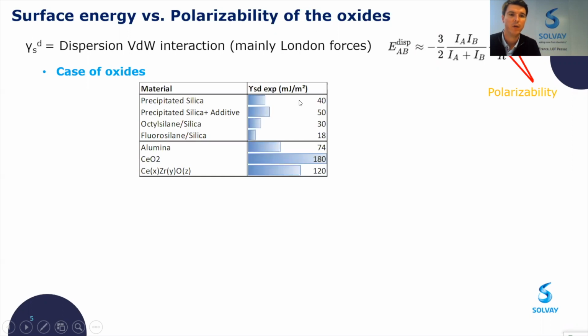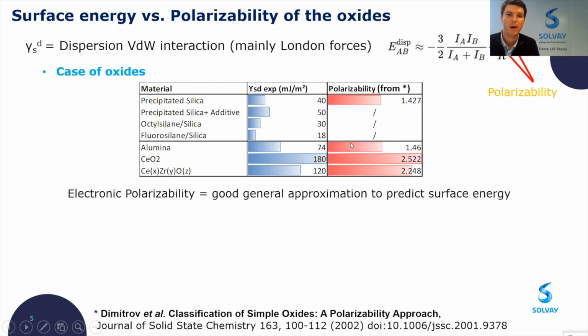In the case of the oxide, we have experimentally determined the surface energy for different kinds of materials like silica, alumina, ceria, zirconia, as you can see here. And when we compare with values of electronic polarizability extracted from literature, you can see a pretty good agreement between these two values, and it can be a good general approximation to predict the surface energy.